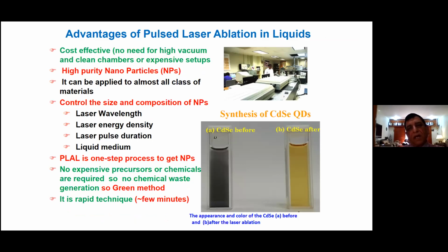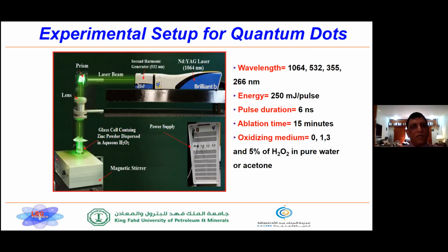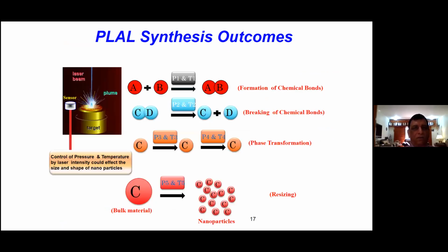So here is one example: cadmium selenide, which is black, but when it becomes a quantum dot, the color completely changes to yellow. This is the setup: we have a neodymium YAG laser, a turning mirror, a focusing lens here, and just a magnetic stirrer. It's a very simple technique and very simple setup, but the beauty is that within 15 minutes, I can generate nanoparticles of the size which I like just by controlling the parameters, while chemical methods sometimes take 3 days, 4 days or more. So it is very cost-effective, very rapid, and a green technique because we don't require any precursor. Just by changing parameters, we can get a lot of outcomes.